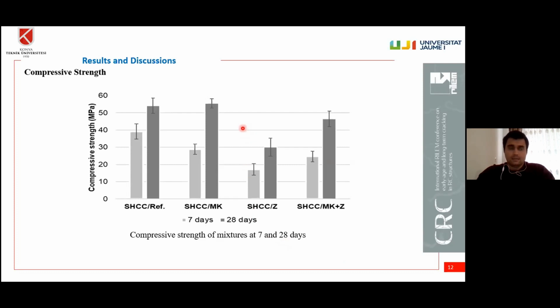To begin with, the sound mechanical properties: you can see the compressive strength of specimens at 7 and 28 days. As you see from the graphs, in the first 7 days, as expected, all mineral admixture bearing specimens had lower mechanical properties than the reference specimens, but at 28 days, the metakaolin was able to present higher compressive strength than the reference specimen.